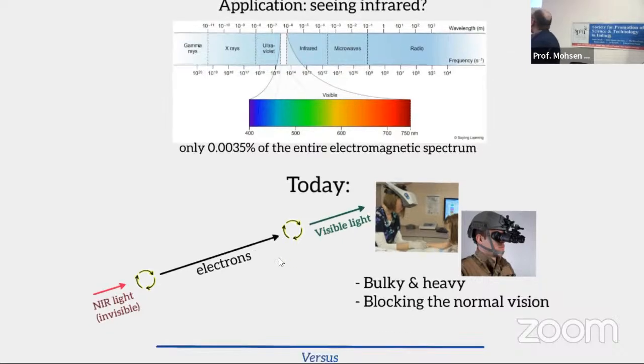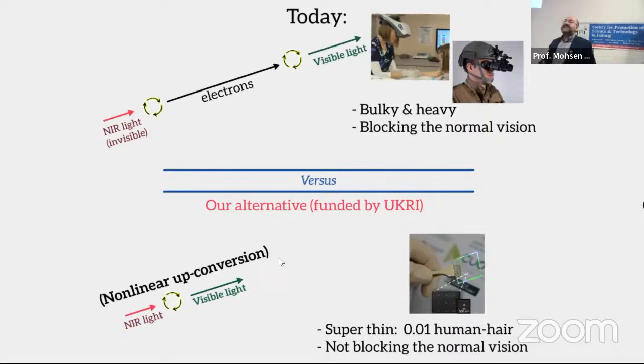So what we propose is that we can engineer nanoparticles that can convert the frequency of the light from near infrared to visible and put them on the surface of glasses around us, like eyeglasses, windows, car windows, ceilings. In this case, we would be able to see the near-infrared light without converting it to electrons. And the importance here is that we do not block our normal vision, because those nanoparticles can be designed in a way that will be transparent in the visible light. I will show you an example shortly. So it means that you can see visible and near-infrared light, not visible or near-infrared light. It is a big thing for the industry, and it can really change our lives.